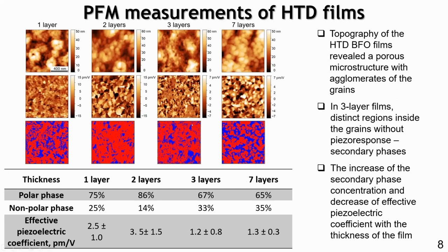If you check the PFM, you see that the PFM contrast is not really so nice. We have some regions which are clearly piezoelectrically active, with black and white in these images, and we have large areas which are not piezoelectrically active. And when we implemented this algorithm which I discussed in the previous slide, we can create such maps of piezoelectrically active and piezoelectrically inactive phases, and we can estimate the fractions of these phases.